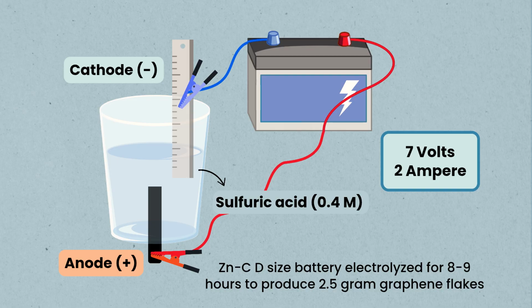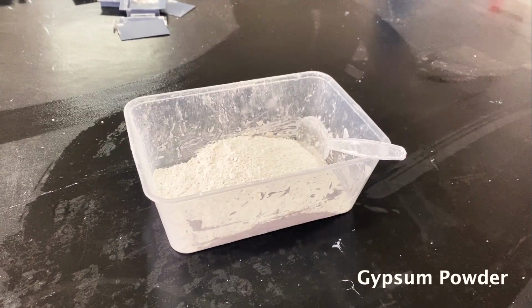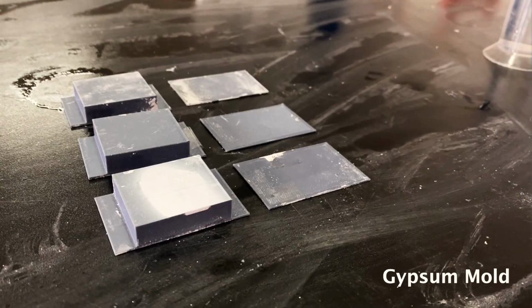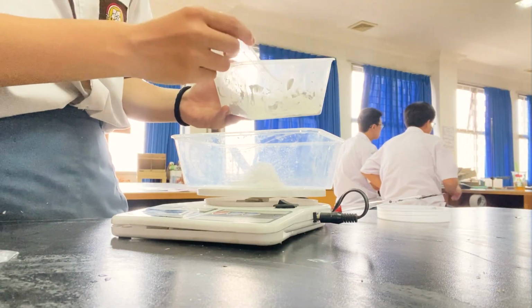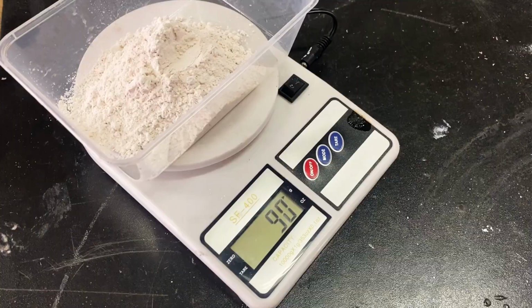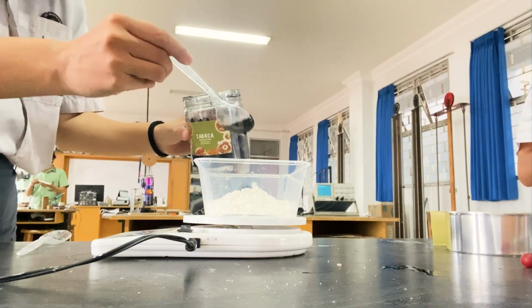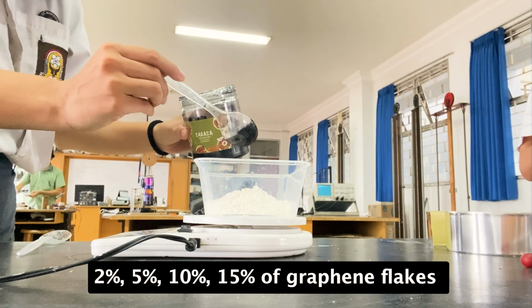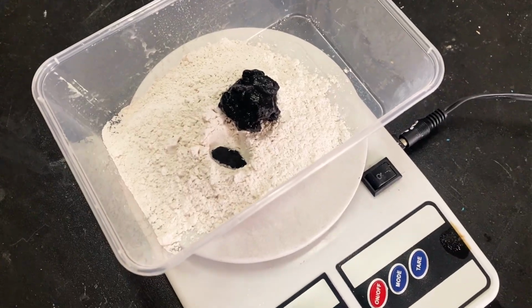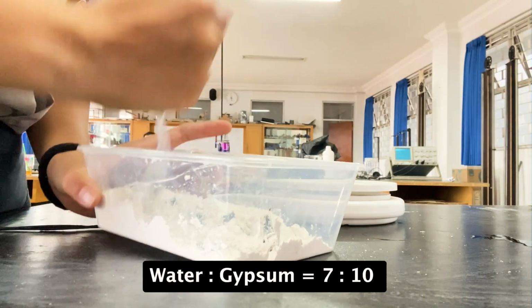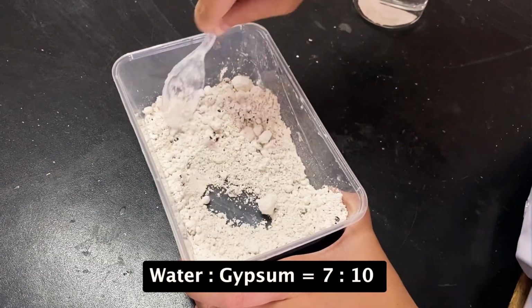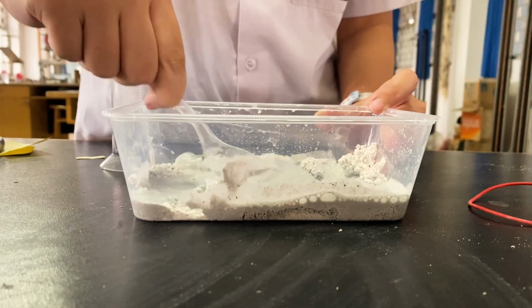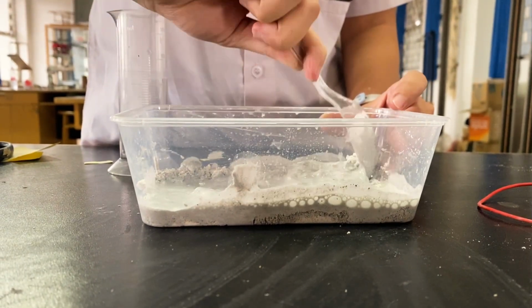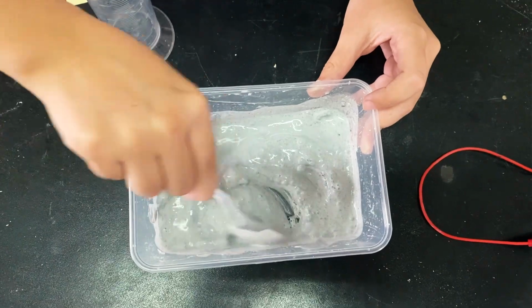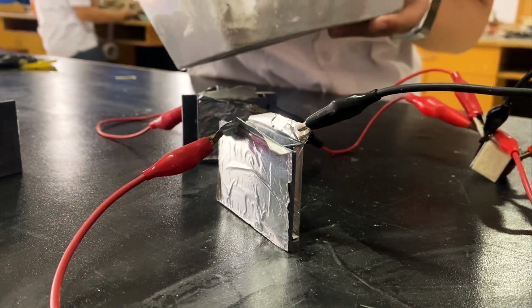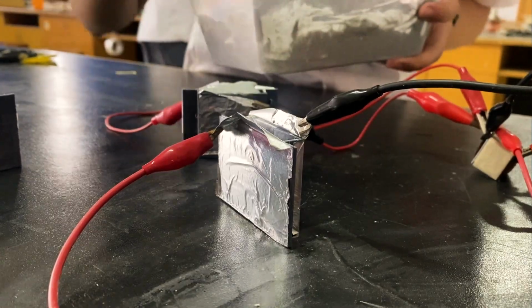To make the carbon gypsum, we need graphene flakes, gypsum powder, water, and gypsum molds. In this study, there are 5 different percentages of graphene flakes in the overall mixture of water and gypsum. Specifically, gypsum without graphene flakes, and 2%, 5%, 10%, and 15% graphene flakes. The graphene flakes are added to the gypsum and mixed. Water is also added with a ratio of gypsum to water of 10:7. After mixing, the mixture is poured into the gypsum molds, then left for 2 days or so until